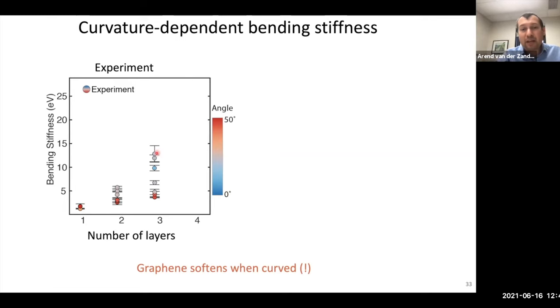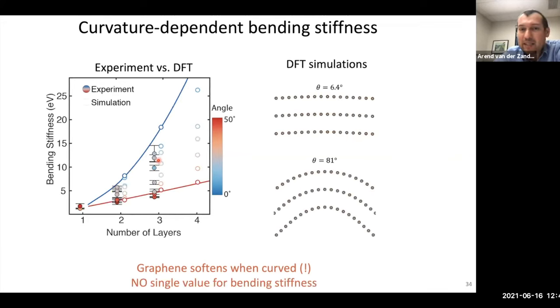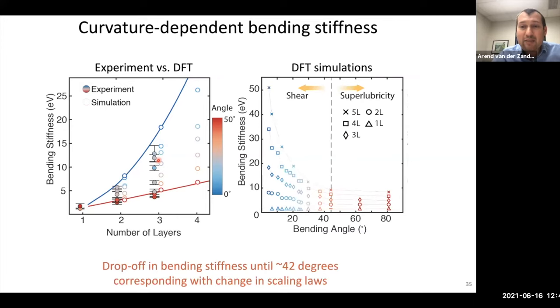When we bend it by a small angle, it's stiffer. And then as you keep on bending, the material actually gets softer and softer. So at higher bending angles, it's a softer material than at low bending angles. This was a little bit confusing, but it actually starts to make sense when you remember that this material is based on atoms. And so as a result, when you're bending it, first the atoms are all locked together, they're lined up. And then as you bend it further, then the atoms stop lining up and now they can slide much more freely. And that leads to a bending angle dependence.